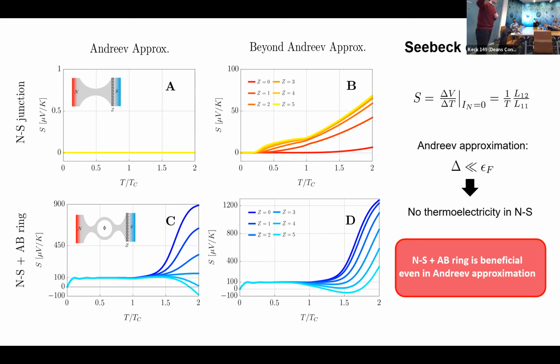Instead, in order to get a finite Seebeck coefficient, you have to go beyond the Andreev approximation, in which case you see that the Seebeck coefficient is finite and also has this monotonically increasing dependence on both temperature and the transparency. So the very important first take-home message from this slide is that, talking about a normal-superconducting Josephson junction, you cannot obtain thermoelectricity if you are in the Andreev approximation regime. To really describe thermoelectricity, you have to go beyond the Andreev approximation, in which case you really can describe the thermoelectrical properties of your system.